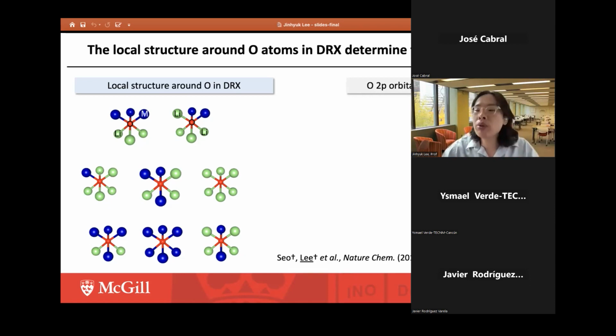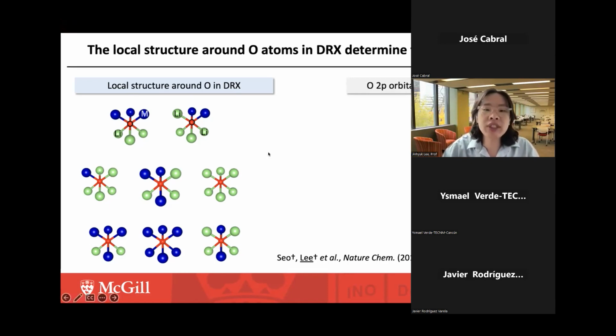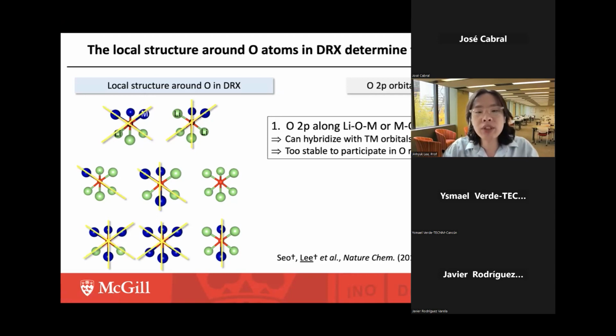Now, we know that oxygen anions have 3 2p orbitals, right? We have 2px, 2pz, and 2py, right? So now we can have 3 branches of the oxygen 2p orbitals. And now if you carefully look at this configuration, we can see that first of all, there can be oxygen 2p orbitals lying along this particular lithium-oxygen-to-metal or metal-oxygen-to-metal direction.